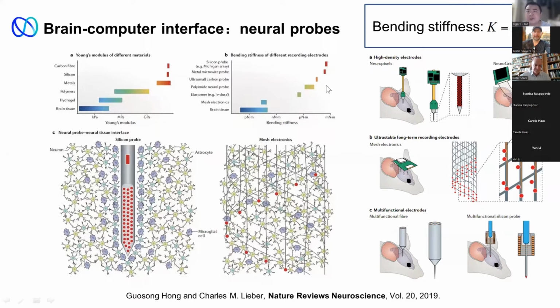For example, if you reduce the thickness by a factor of 10, you can reduce the bending stiffness by a factor of 1,000, which means with the same materials, just with a thinner format of this neuron probe, it can be 1,000 times softer or more flexible, if you do the simple math. So that's why in brain-computer interfaces, especially for people trying to build better neuron probes, many have tried to use soft neuron probes. How to make it softer? Simply make it thinner. So that's how you can choose the right materials and improve performance by reducing the bending stiffness by simply reducing the thickness.